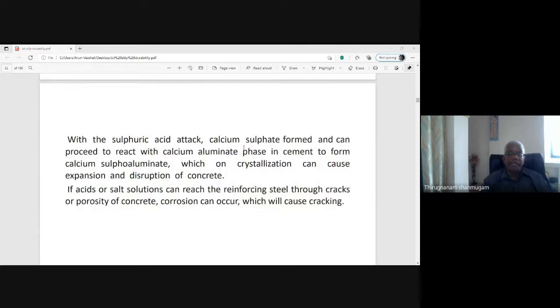With sulfuric acid attack, calcium sulfate is formed and can proceed to react with the calcium aluminate phase in cement to form calcium sulfoaluminate, similar to the sulfate attack, which on crystallization can cause expansion and disruption of the concrete. If acid solutions can reach the reinforcing steel through cracks or porosity of concrete, corrosion can occur, which will cause cracking. That is one of the major points in the acid attack or the chemical attack, sulfate attack. So corrosion can occur, which will cause cracking of the structure and finally failure of the structure.